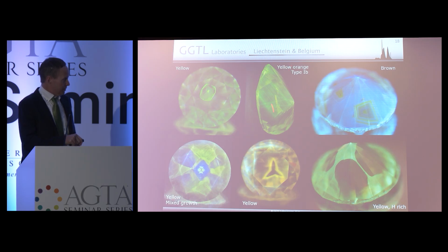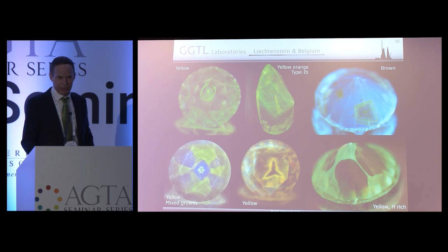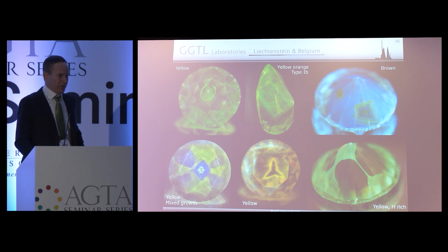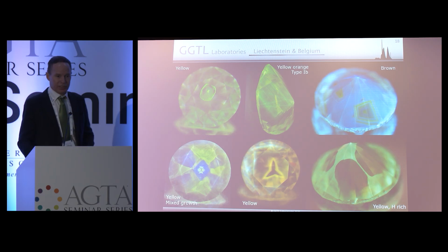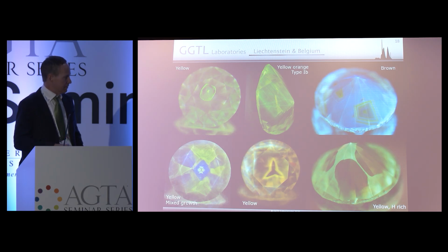Here, a yellow-orange type 1B. You can see the straight layers going in one direction here. That's from plastic deformation. So this stone had some plastic deformation post-growth, and that causes these dislocations along the octahedral direction and accumulations of H3 centers, which give you this green fluorescence.